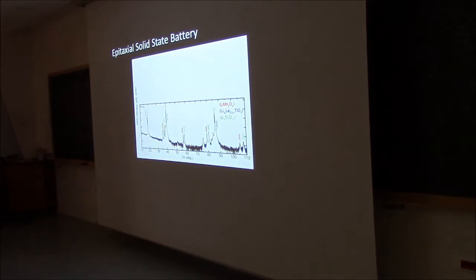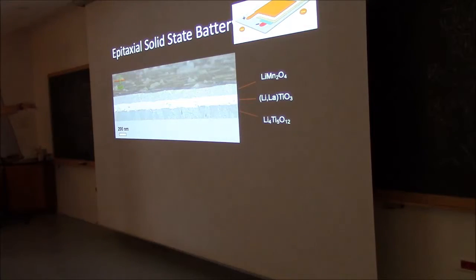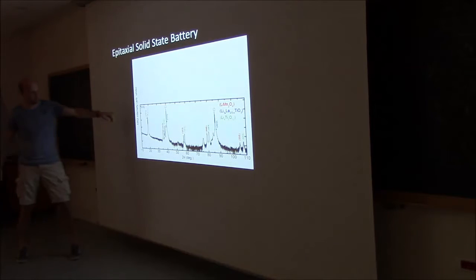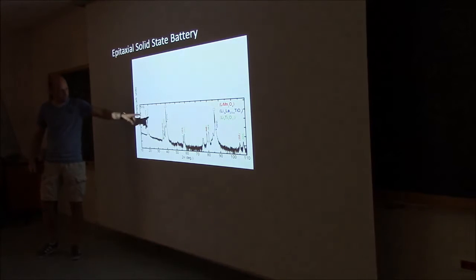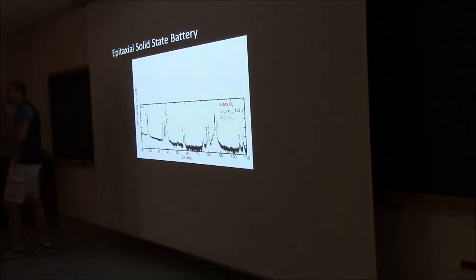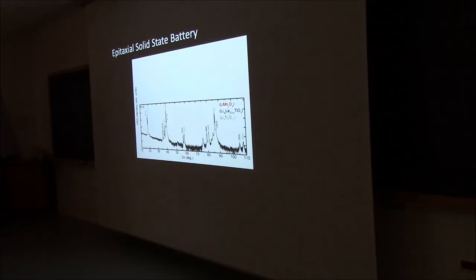Structurally, we can see, if we do it on the 1-1 orientation, then you have these smooth layers. In your X-ray diffraction, you can see the peaks of the substrate and the peaks of the 3 different layers, they're all oriented, so that's okay. Structurally, it's fine. It's just the details of the specific stoichiometry.